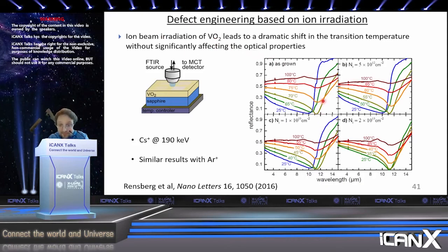You can see that the same feature in all of these reflectance curves occur at very different temperatures, from 70 degrees at the phase transition for the intrinsic material all the way down to room temperature. And this is because the ion irradiation, ion bombardment, actually results in defects which cause strain in the material, and strain is known to be one of the factors that can decrease the phase transition temperature of VO2. And so you can use any sort of ion beam. Here we use cesium or argon or various types of ions to just damage the film intentionally a little bit.